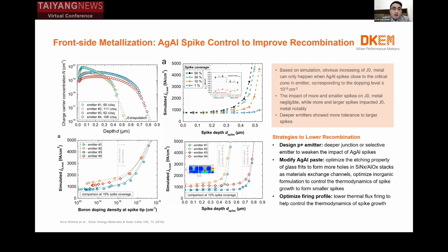On this page, we would like to talk about how to control the spikes to improve the recombination. Actually, based on the simulation, we learned two things. First, smaller spikes have almost no impact on the J0,metal, but too big size spikes impact the J0,metal greatly. Second, deeper emitters show more tolerance to large spikes.